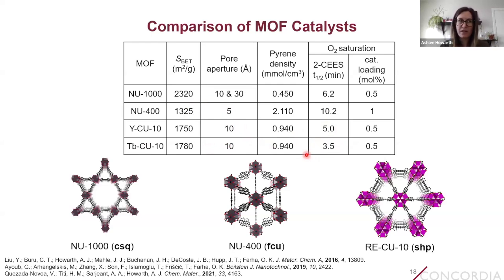And so this is something that we thought was really interesting, because this balance between pore aperture size and pyrene density is dictated by MOF topology. And this SHP topology of rare earth Cu10 has so far only been shown to be accessible through the use of rare earth elements, which generate the nonanuclear cluster node that's required to make this MOF and this topology.